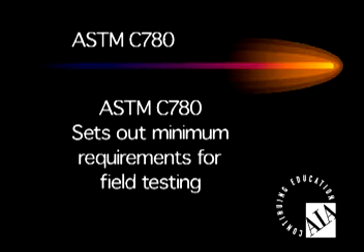So you've just proved that most of these tests don't really tell you about the mortar in the wall. I have got to test my field mortar — can't I just pick a number like 50% or 70% of the C-270 strength? The short answer is no. When you test the mortar in the field, you are measuring the consistency of batching and mixing by measuring its strength. You can do that, but you must also have a minimum set of standards for the making, curing, protecting, and transporting of those specimens. Let's look at ASTM C-780 in detail.